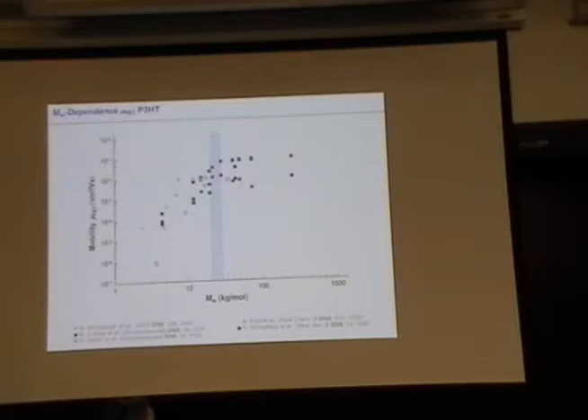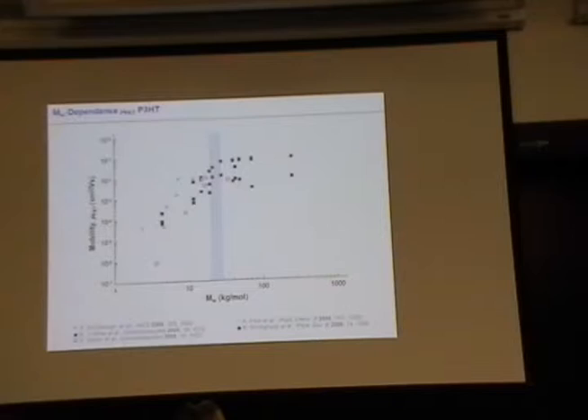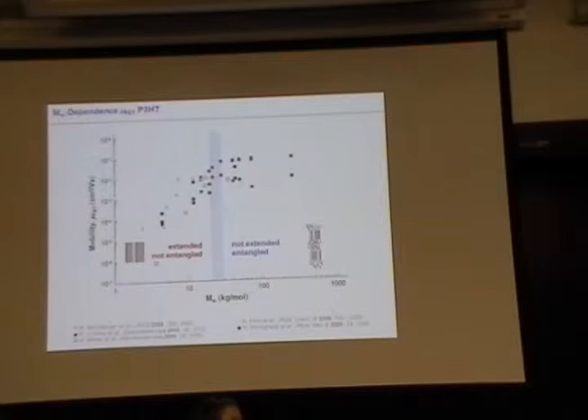And now we look at electronics — for an OPV conference or workshop. You see it actually correlates strikingly when you look at field effect mobility: you make a transistor with your semiconductor where the mobility essentially saturates. This was a graph that puzzled me for years, because I would have assumed intuitively that small molecular weight materials should crystallize faster and should have better mobility. Here you really see end groups in small molecules — small molecular weight molecules can be detrimental for charge transport, most likely because of grain boundaries.